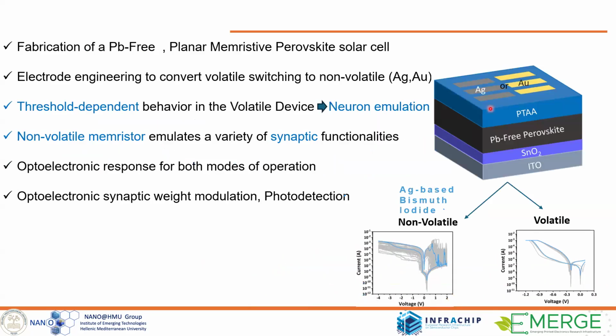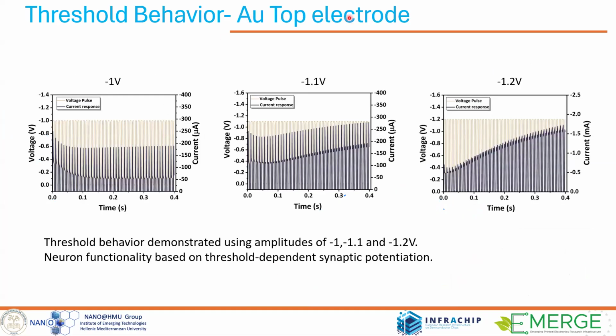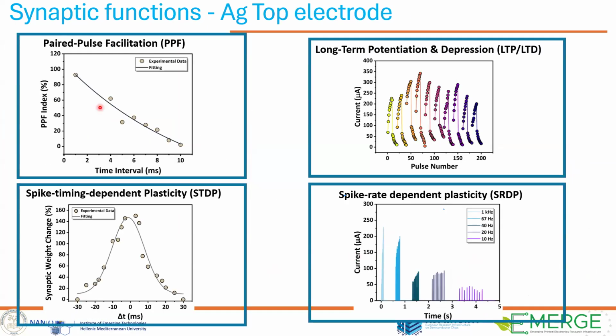So this is the configuration. We also changed the structure. Now it's a normal one: this is ETL, perovskite, HTL, and then the top electrode, and ITO is the transparent electrode on the bottom. Typical non-volatile curves are shown on the left with silver-based and volatile with gold-based on the right. We demonstrated typical threshold behavior for the gold-based electrodes by changing the amplitude of the pulses. Then for the silver-based non-volatile memristive devices, typical synaptic protocols, such as paired-pulse facilitation index, long-term potentiation and depression, spike-timing-dependent plasticity, and spike-rate-dependent plasticity have already been demonstrated using these devices.